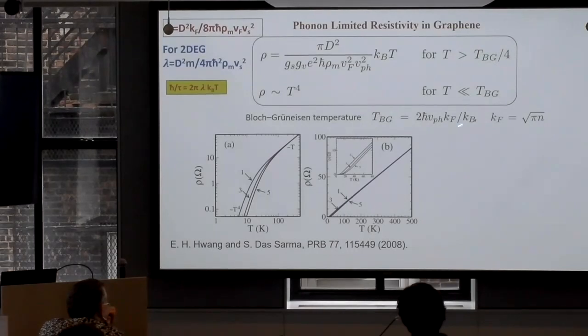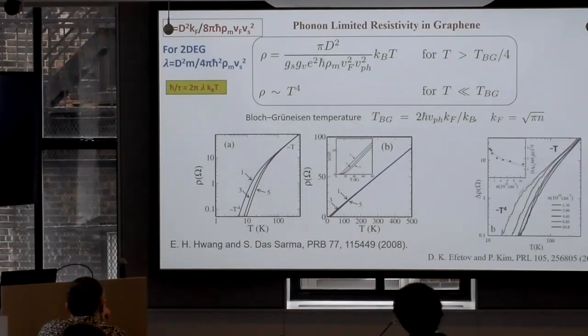The Bloch-Grüneisen temperature is nothing other than this quantity. It's the energy of a phonon with 2kF scattering, because the most dominant resistive scattering is an electron going in this direction and reversing its path. So that's 2kF. That's the most dominant scattering, and that's the temperature scale. So we should see this. We made this prediction and produced results using the known parameters. This is their experiment. I'll just say it agrees quantitatively with this theory.